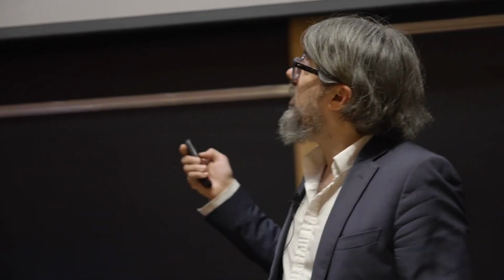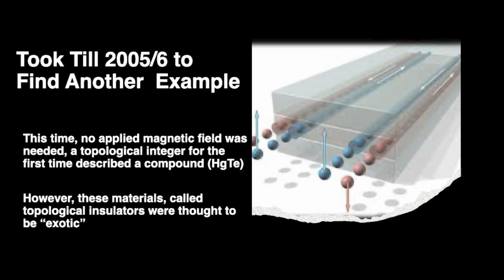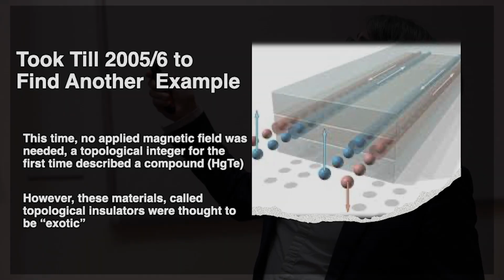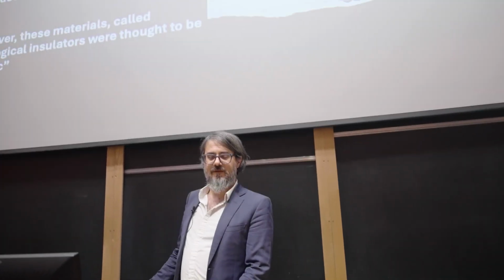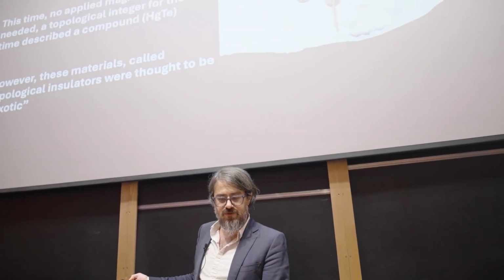And this integer really has to do with edge states. And in the topological integers, I'll get back to some other integers a little bit later. For example, in this mercury telluride quantum spin Hall effect that Paolo mentioned, the integer is the number of edge states that are going in the left and right directions. They always have to come in pairs on the edge. If you have an even number of them, you're trivial. If you have an odd number of them, you're non-trivial.